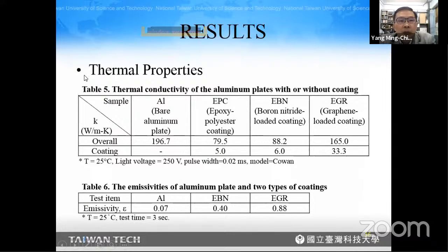The result, first, is about the thermal properties of this plate. We can see that the overall conductivity for aluminum is 196.7 watts per meter per Kelvin, and for a coated plate it dropped to 79.5. With the blending of boron nitride, the conductivity increased to 88.2, and 6 was attributed to the coating.